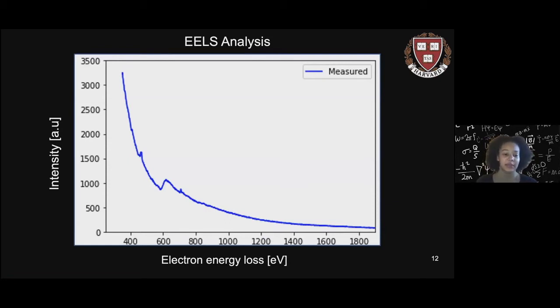So to give a bit of an explanation about how this analysis process works, as I explained here, we measure along a spectrum of energy loss the intensity of how many electrons lost that specific amount of energy. And you'll note that this follows a power law function with peaks at specific intensities. So if you recall in the previous slide, I explained how each element has a known amount of energy loss when it hits an electron beam of a given energy. So thus we can identify titanium, which is known to lose approximately 500 electron volts of energy, tellurium, as well as oxygen. And these are all three elements that are present in the top layers of our sample.